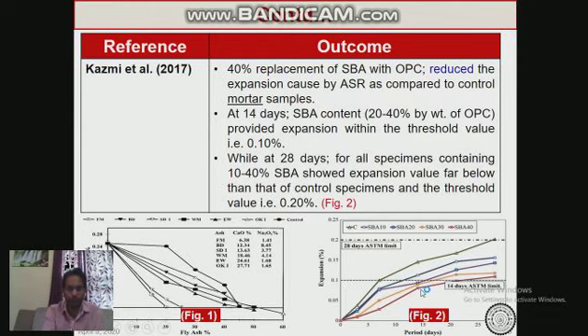For these three graphs, while for 28 days, the replacement of OPC with SBA up to 40% showed that the expansion was within the threshold value, that is 0.2 percentage. Here we can see the graph for expansion at 28 days of SBA incorporated concrete, and this is for the control sample.